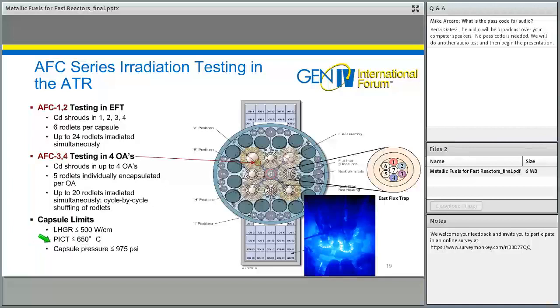We can get the cladding temperature as high as 650. That's not where we typically test it. Typically more about 550. But it's not exposed to the water coolant. It's just exposed to inert capsule gas.